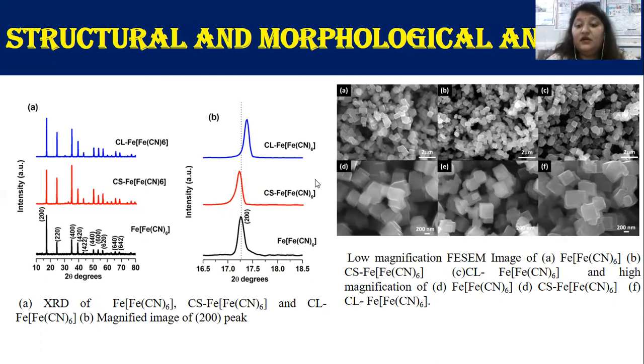From figure B, you can see that upon sodiation, the 200 peak showed a peak shift towards the lower angle, indicating lattice expansion, while the same 200 peak upon lithiation shifted toward a higher angle, indicating lattice compression.